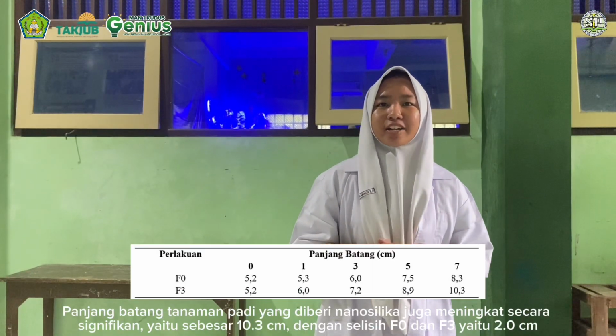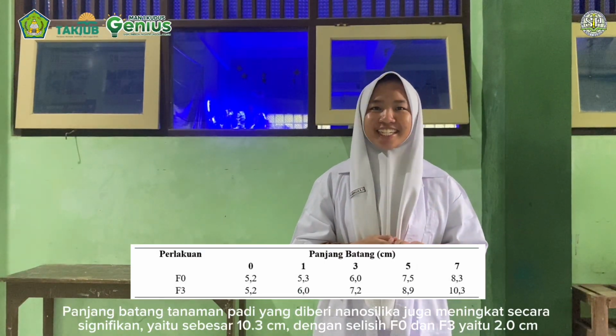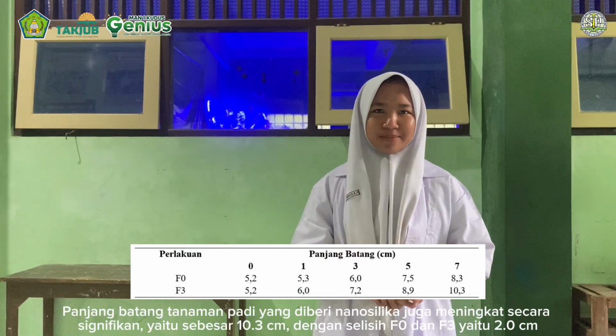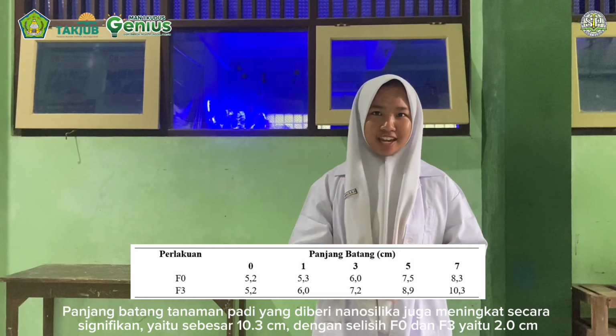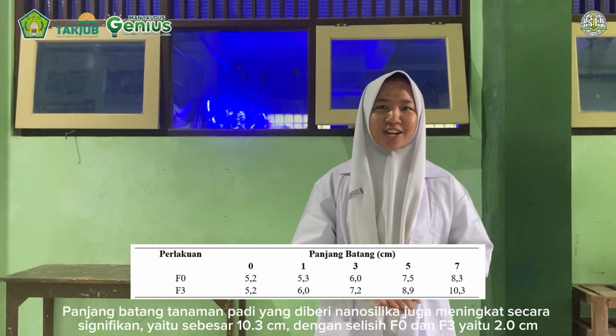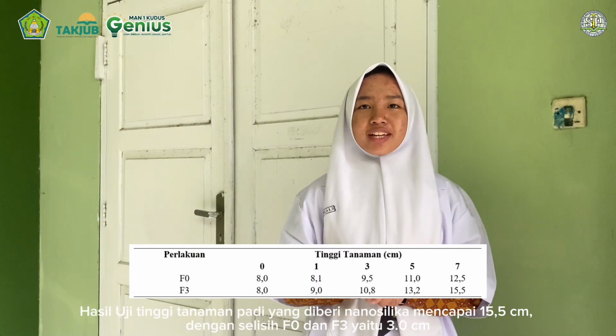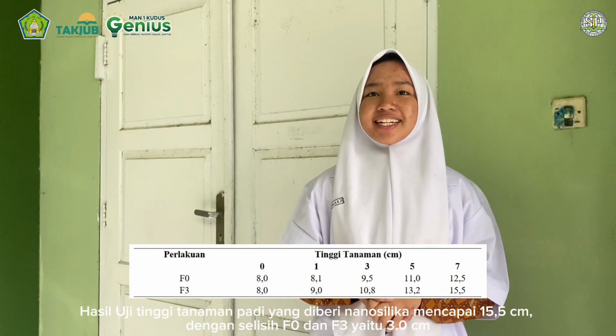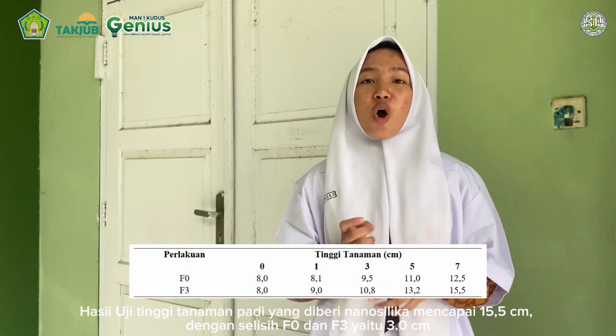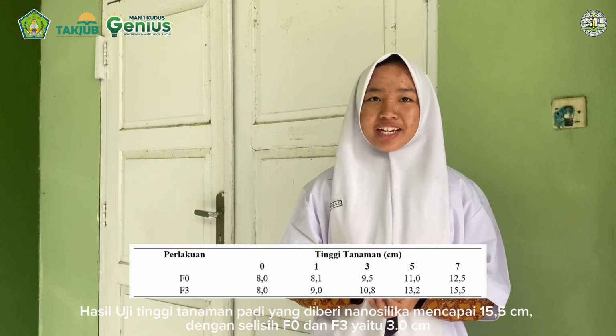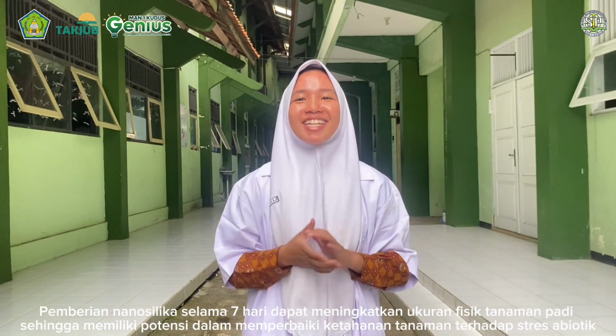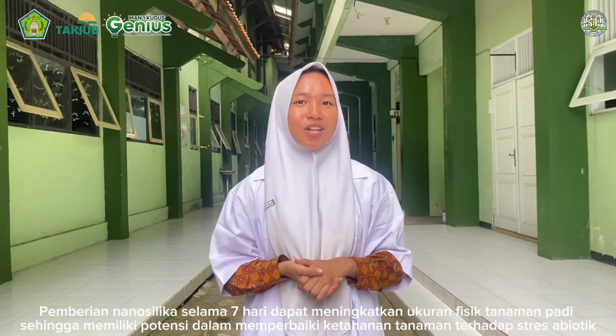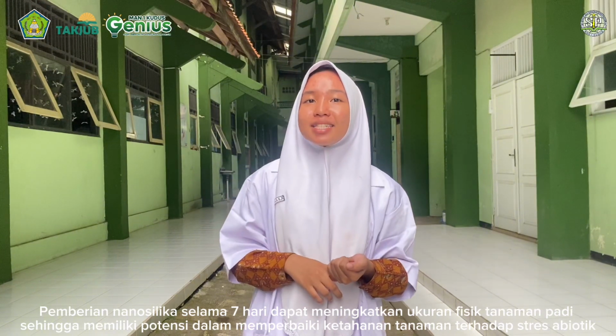The stem length of rice plants fed with nanosilica also increased significantly, namely by 10.3 cm, with a difference between F0 and F3 of 2.0 cm. The result of the height test of rice plants fed with nanosilica reached 15.5 cm, with a difference between F0 and F3 of 3.0 cm. The application of nanosilica for 7 days can increase the physical size of rice plants so that it has the potential to improve plant resistance to abiotic stress and increase the efficiency of water and nutrient use.